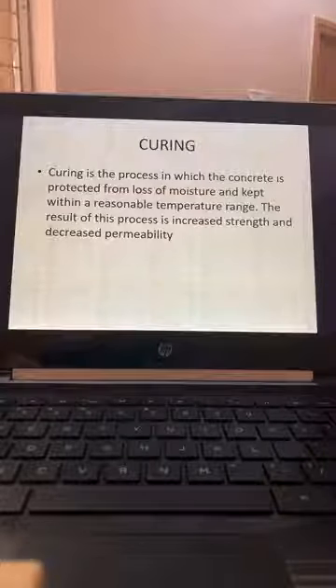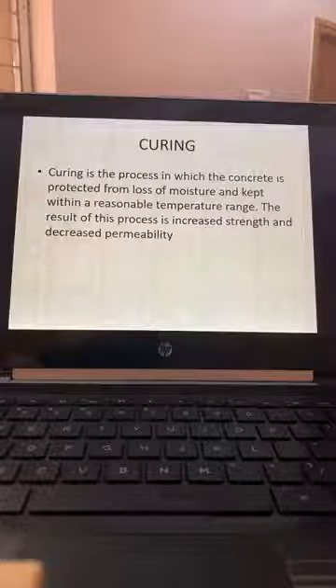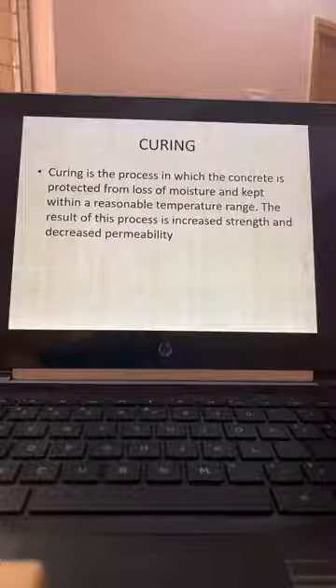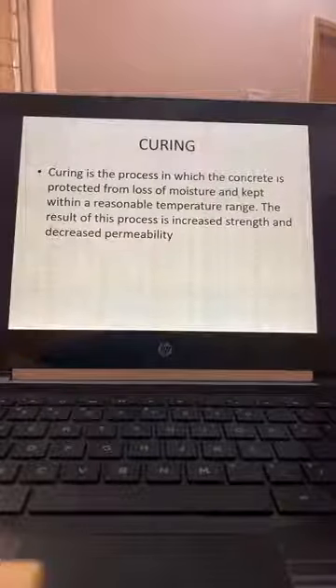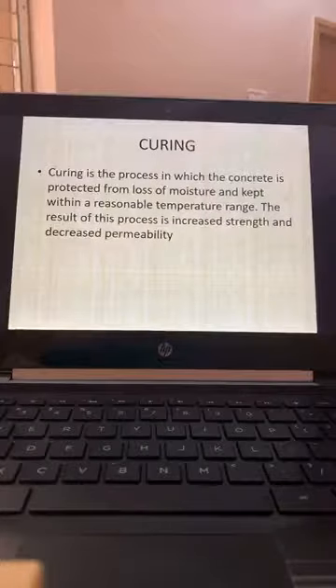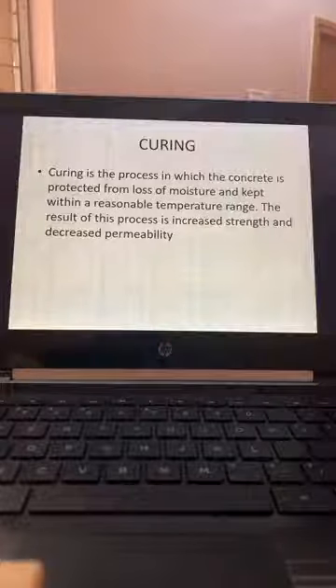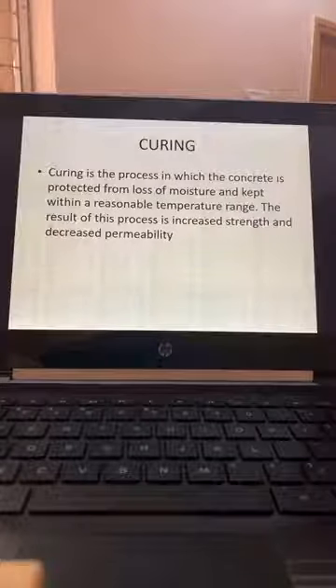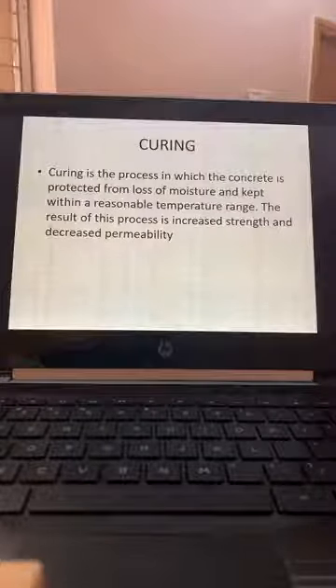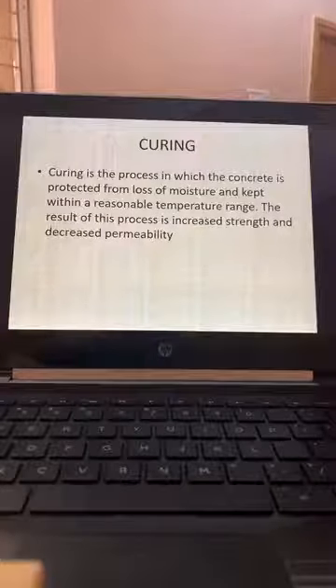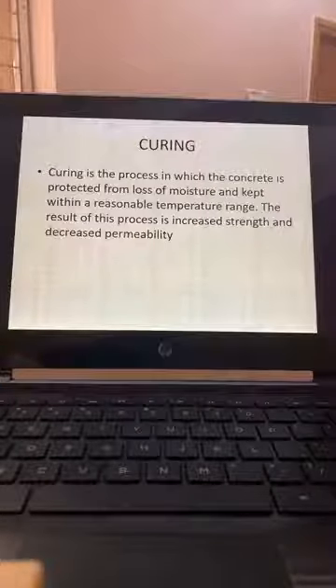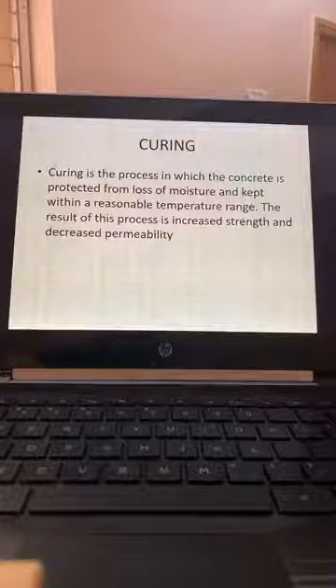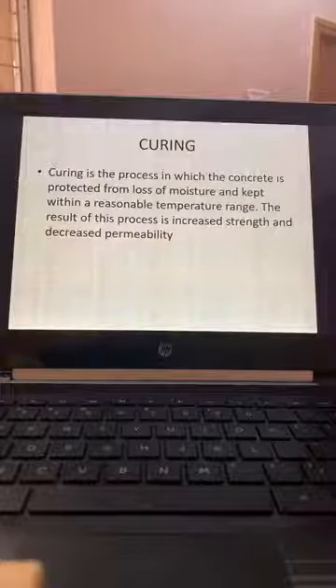For 14 days the hydration process continues. Minimum curing period for any concrete should be 14 days and preferably up to 28 days. Please don't make curing tanks at the site. Marry the cube to the element for which you have taken the cube — if you are collecting cubes for a slab, put those cubes on the slab only so that curing of the slab and curing of the cube are the same.